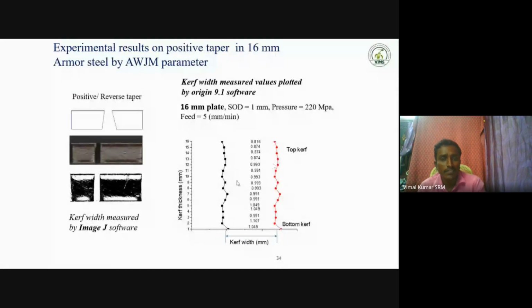Like that, for the 16 mm plates also, we measure the values for 16 readings, and then plot them in the graph. We can see the alignment. It is also not a straight cut. Some physical curve is there in the cut surface, which our eye identifies. At the same time, here we also see some angle deviation for each mm thickness of the 16 mm plate. Here SOD is 1 mm, pressure 220 megapascal, feed rate is 5 mm. So this is not suitable for the 16 mm plate.